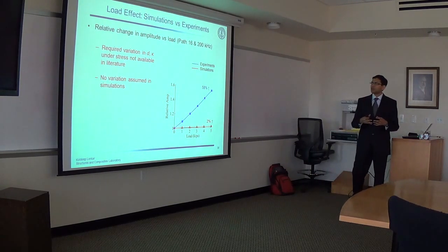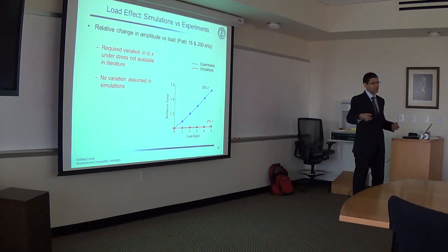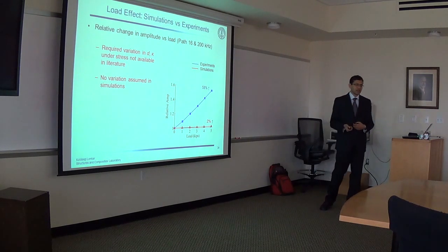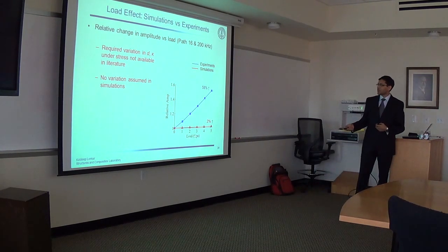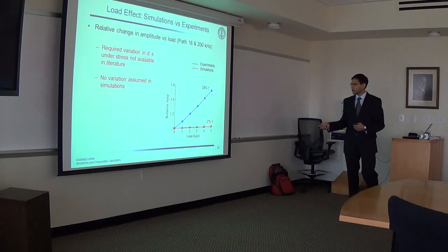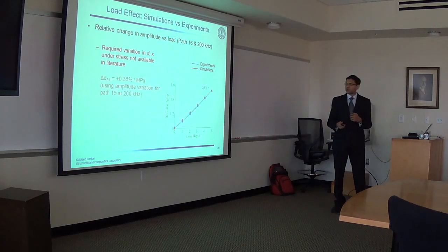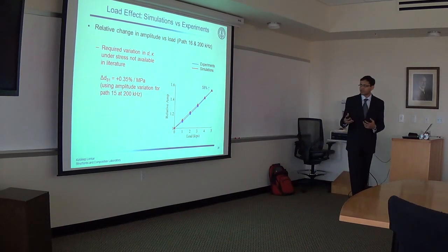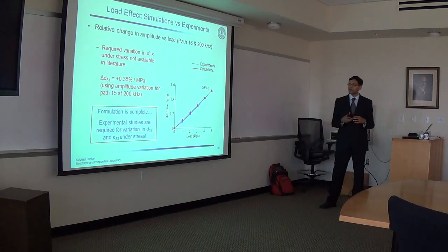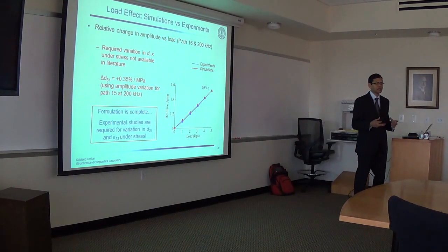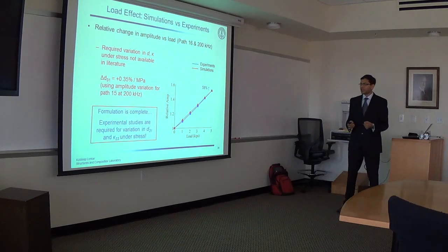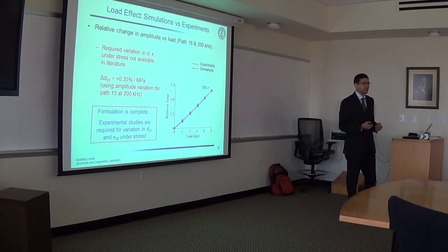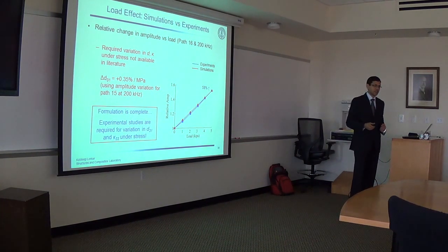Unfortunately, the required variation in D31 and kappa 33 under this tensile load is not available in literature, so we didn't assume any variation in simulations. As you can see, we cannot capture the variation in the signal amplitude with load in the simulations. We can assume some variation in D31 and capture the variation in the sensor signal amplitude. But here I want to emphasize that the formulation, the governing equations and the spectral element formulation is complete. We need experimental studies to get the required variation in D31 and kappa 33 under tensile stress.